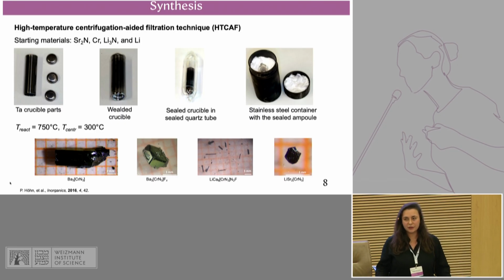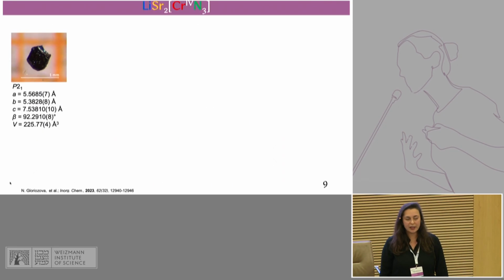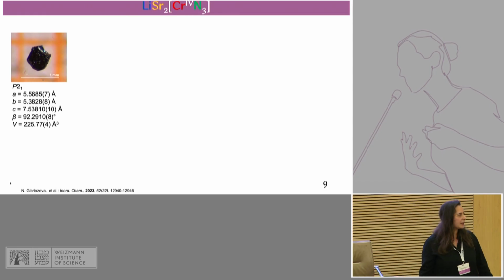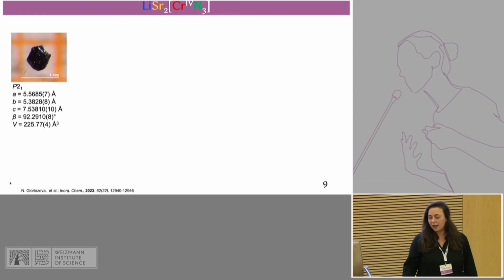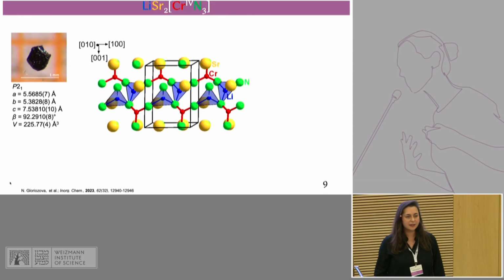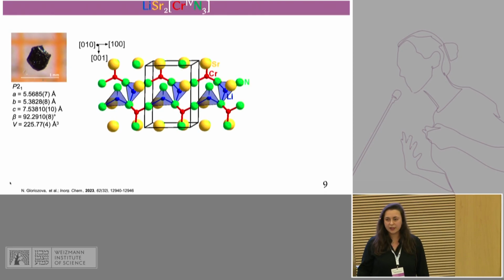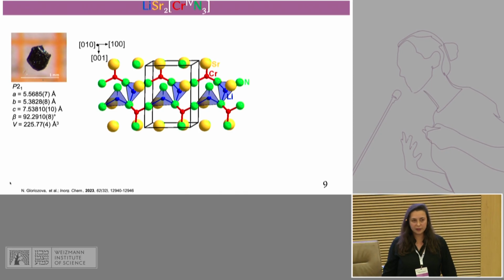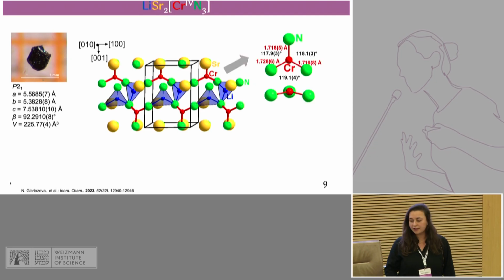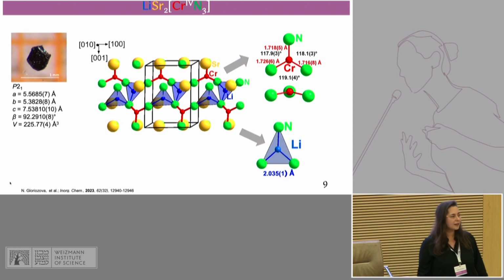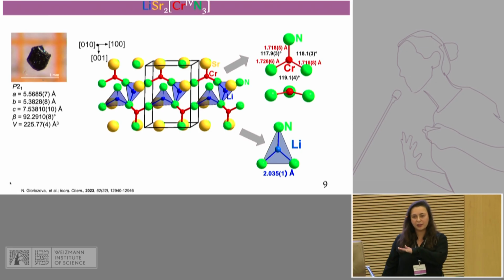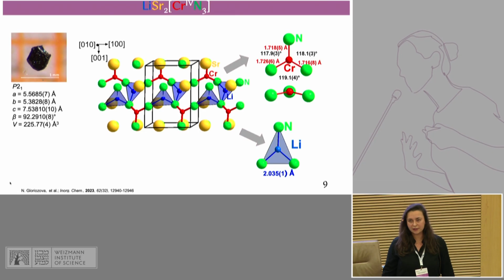So, now to the results that we obtained. We were able to grow black metallic crystals and obtain the crystal structure, which can be visualized in the following way. It's quite complex, but we will divide it into simpler parts. Firstly, trigonal, slightly pyramidal units of CrN3. Secondly, slightly pyramidal lithium-nitrogen units, which form slabs along the c direction in the unit cells.